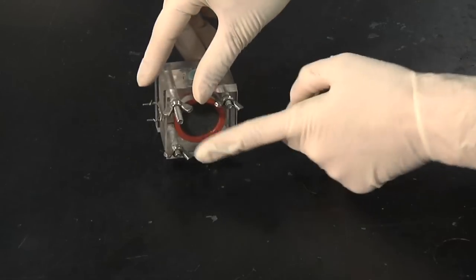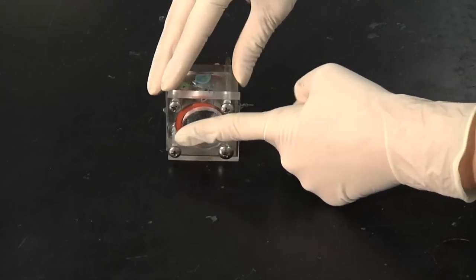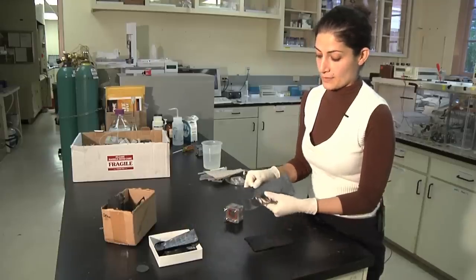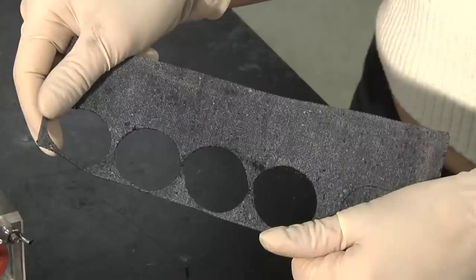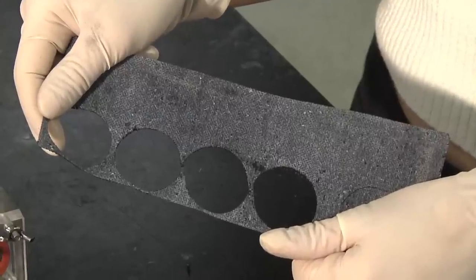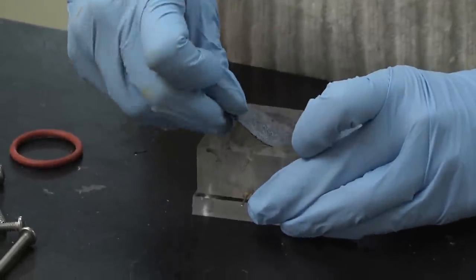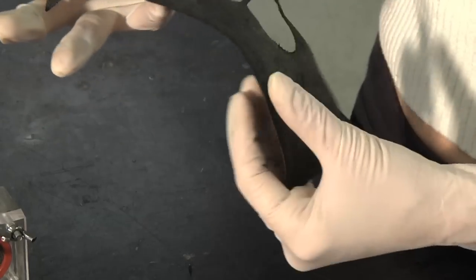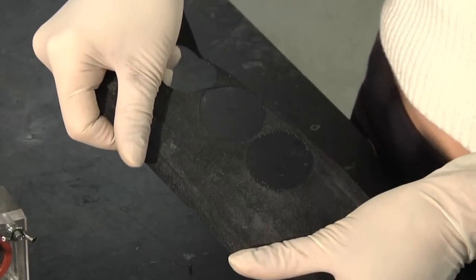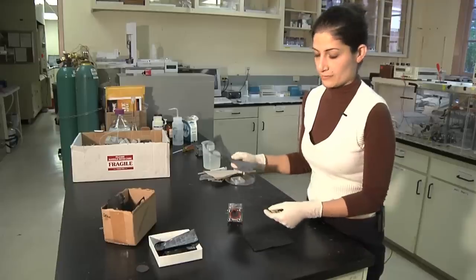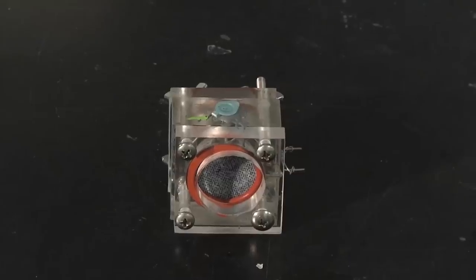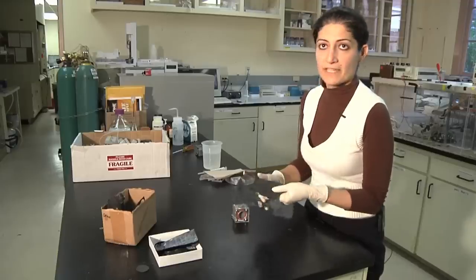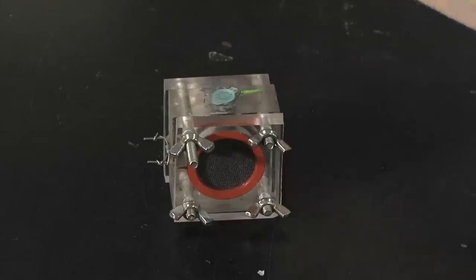So then the electrons from the anode flow into the cathode. The same carbon cloth, it is painted by PTFE from one side, that is hydrophobic, so to hold the water inside the MFC. And from the other side by platinum, that is the catalyst. And so this is a cathode that is on this side of the MFC. And the carbon cloth without the PTFE and the platinum goes in the anode.